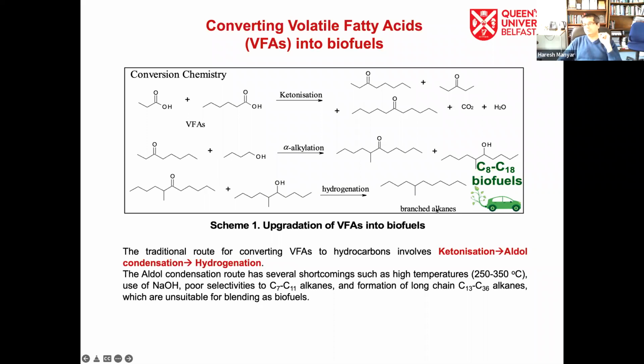The advantage of this process is that, on one hand, the feedstocks are dilute, present in water, but the product which we make here is hydrocarbon, which is immiscible with water. So the direct layer-to-layer separation of the hydrocarbons from water saves a lot of energy. It is not an energy intensive operation requiring distillation of the hydrocarbons from water. If you were to separate the fatty acids from water, you would require a lot of energy and it would become an energy intensive process. But by following this series of successive cascade steps, we produce a water immiscible product. Then it directly becomes a liquid-liquid separation, which is a much more energy efficient process.